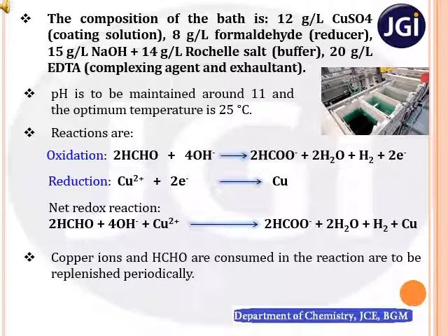At the same time, formaldehyde undergoes oxidation to provide electrons for the reduction of copper, so formaldehyde is also decreasing in the plating bath. In order to get a uniform coating of copper, a desired concentration of copper ions and formaldehyde must be maintained. For that, these two are to be added continuously or periodically to the plating bath. Control of metal content and pH are important. If you are not maintaining the concentration of metal ion, you may not get uniform deposition of copper. Instead, you may get a burnt or uneven deposition onto the substrate surface.